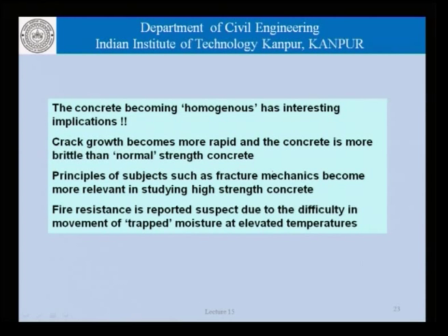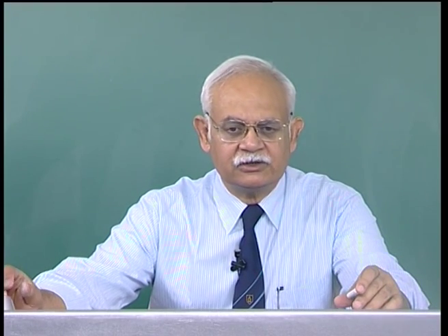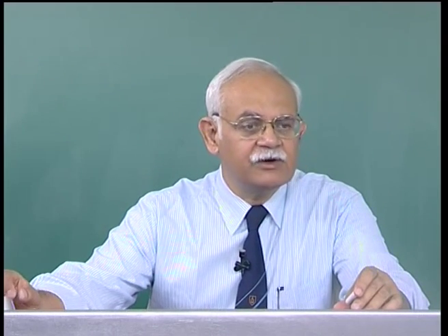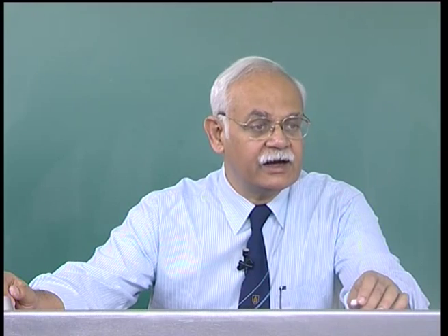As far as properties of high strength concrete are concerned, there is the fire resistance, which is reported to be suspect due to the difficulty in the movement of trapped moisture at elevated temperatures. Concrete could have some moisture trapped inside, and that moisture must be able to escape in the event of fire, because the temperature in the concrete rises. Now, in the case of high strength concrete, because of a different kind of pore system, that water finds it difficult to escape. And if the water cannot escape, it gets converted to vapor, exerts pressure and causes local, well, if you want to call them explosions, which damage the concrete,